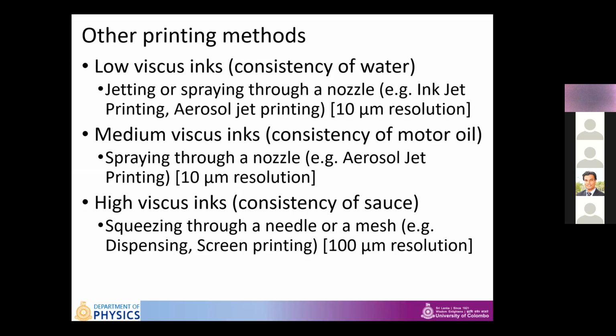If the ink has consistency of motor oil, still aerosol jet printing can handle it. If the ink that you want to print is of consistency of tomato sauce, you can use some form of a syringe dispensing mechanism or screen printing, meaning you can squeeze the ink through a needle or a mesh. The screen printing is the same technique that you use to print t-shirts. Using these two methods, you can achieve about 100 micron resolutions. And in screen printing, if the technique is sophisticated, you can go down to about 50 micron, but very challenging.